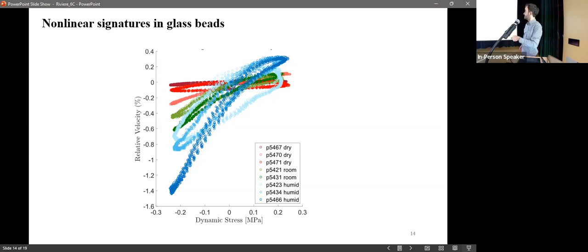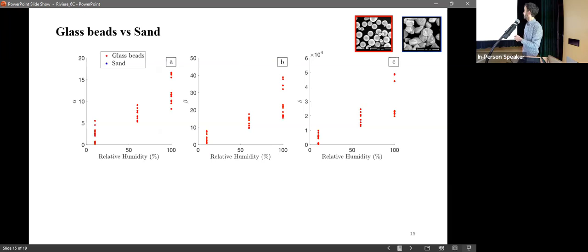And when we extract the nonlinear parameters from that, we see this. All of these are nonlinear parameters, alpha, beta, delta, related to the softening, the slope, the curvature, and so on. We see that the three parameters are increasing with relative humidity. So we see a strong effect. The problem is that all the nonlinear parameters are increasing, so it's not very helpful to try to distinguish what mechanism is what. So it doesn't really help.